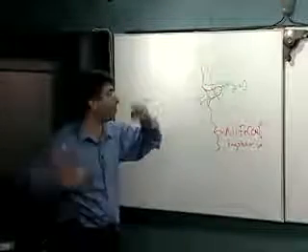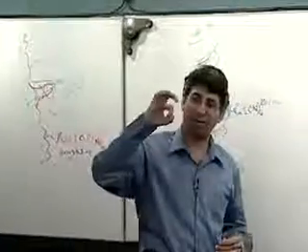So what we're thinking is, this enzyme comes up and hits this electrode, and even if there is some magic spot where the flavin unit gets close enough that we can push the electron in there, just tunnel it in, on average we're not going to hit that spot. We're going to hit randomly. However, we know that this surface is net anionic, all those cyanide ligands on the surface, and we know that there is a ring of negative charge around the opening of the active site of glucose oxidase.